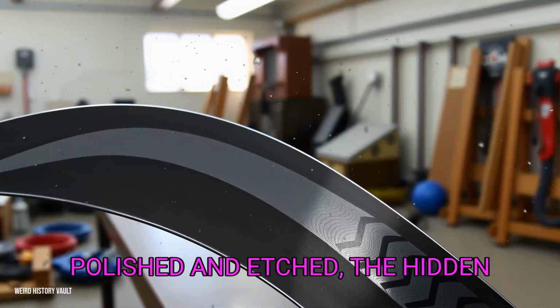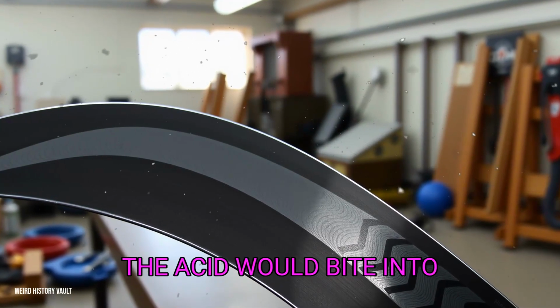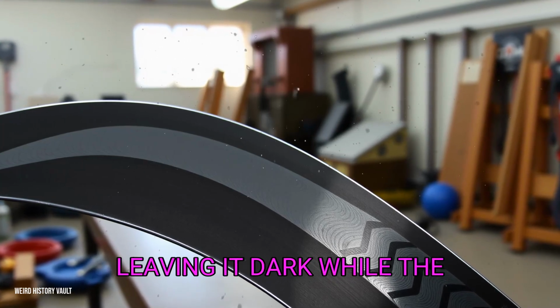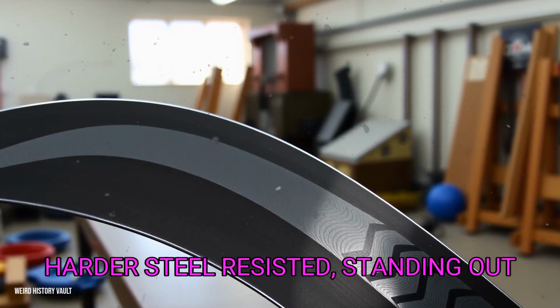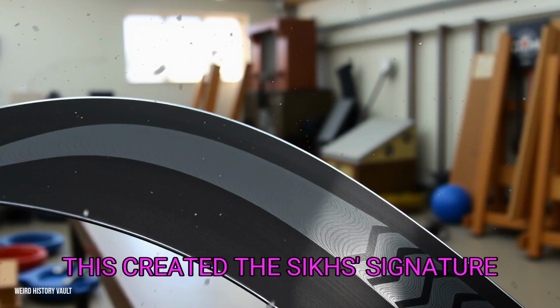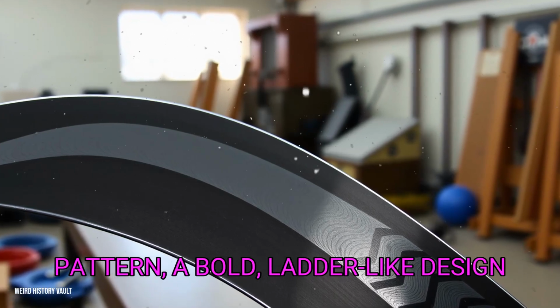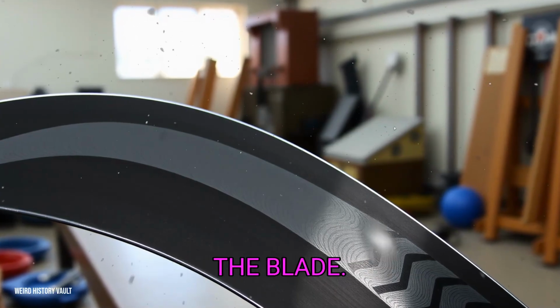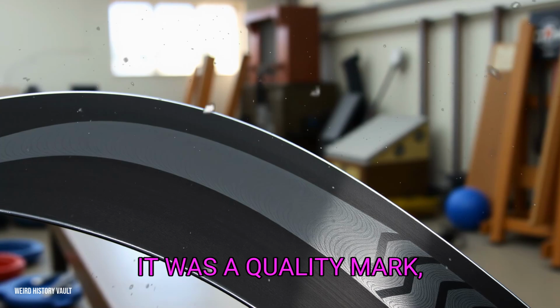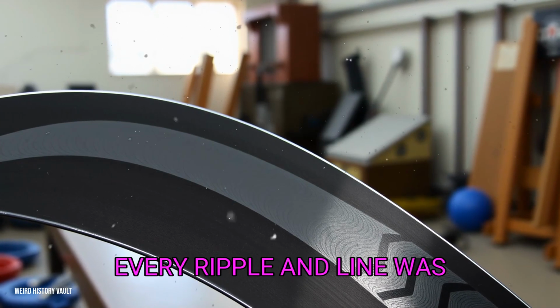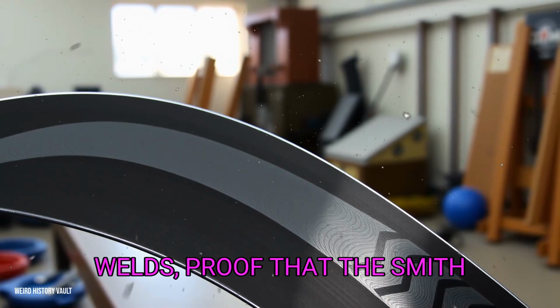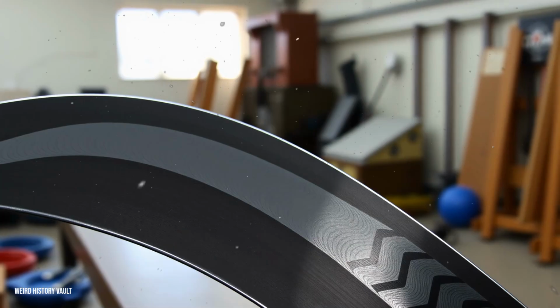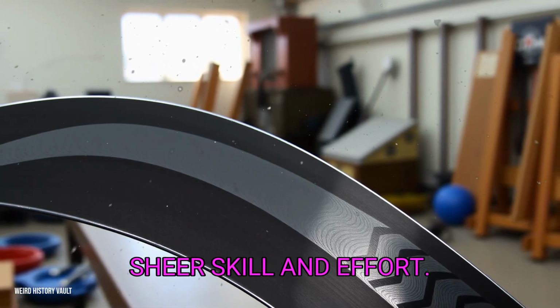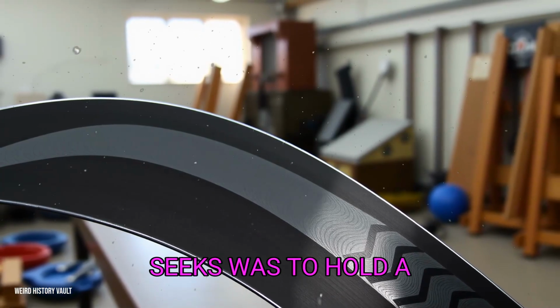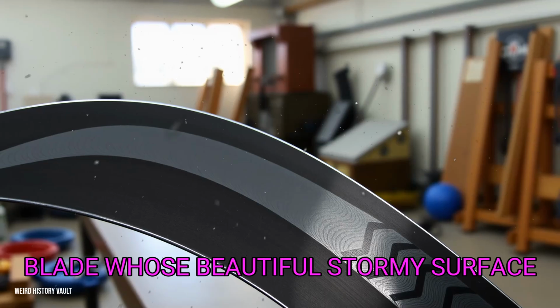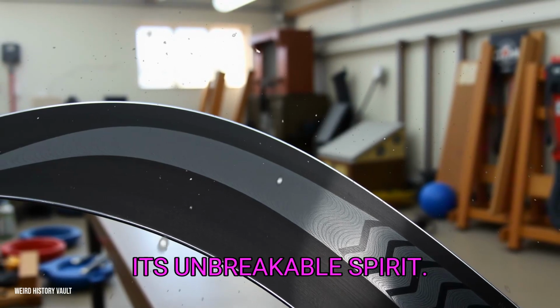When the finished Seax was polished and etched, the hidden labor was revealed. The acid would bite into the softer iron more deeply, leaving it dark, while the harder steel resisted, standing out in silvery relief. This created the Seax's signature pattern, a bold, ladder-like design or a swirling, stormy grain that ran the length of the blade. This was not mere decoration, it was a quality mark, a visible guarantee. Every ripple and line was a map of the countless welds, proof that the smith had successfully homogenized the flawed iron, purging its weaknesses through sheer skill and effort. To own a pattern-welded Seax was to hold a piece of transformed earth, a blade whose beautiful, stormy surface was a direct testament to its unbreakable spirit.